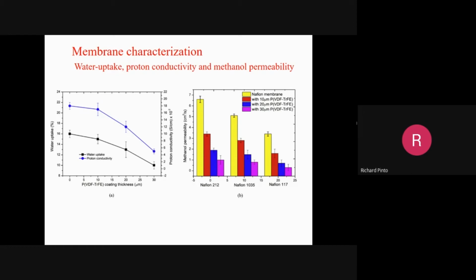Then proton conductivity is just the conductivity of the proton, defined here in Siemens per centimeter. The right side is the proton conductivity, the left side is the water uptake percentage. As we increase the PVDF-TrFE coating thickness, both come down, which is quite reasonable, because water uptake will be reduced because of the coating. At the same time, membrane conductivity will also be reduced because of the coating.